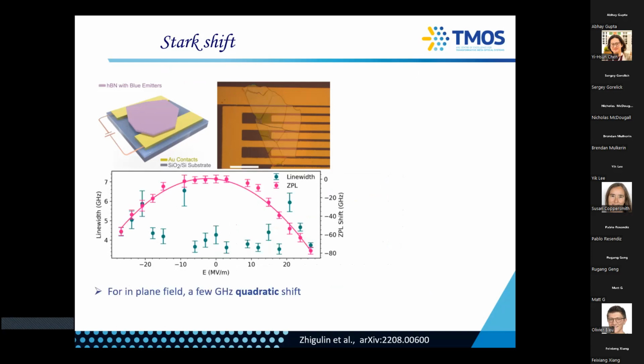Here you would have the ZPL following this parabolic behavior, which means that again there is no linear Stark shift, it's only a quadratic effect. So it's a very minor effect on the structure. So the structure should be very, very symmetrical. And again, because we work with 2D materials, there's almost no geometry that will give you inversion symmetry.